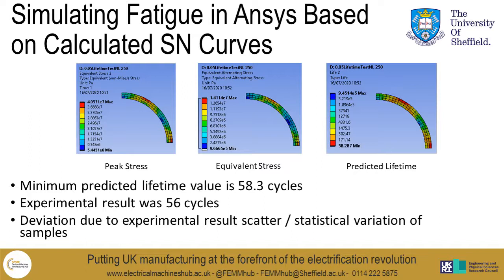You can see here the minimum predicted lifetime is 58.3 cycles. The sample which we were comparing it to experimentally lasted for 56 cycles, which you can see is quite a good correlation between the two results.